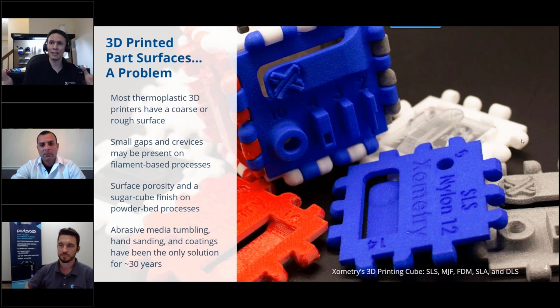Which, unlike cutting parts down from a solid blank of material with a smooth tool that leaves a smooth surface, I am taking a lesser material like a filament or a powder and fusing it up in order to create those parts. And inherently in that process, I'm building in small gaps and surface roughness from powder-to-powder interaction. There are ways to introduce things that can cause mechanical issues or even surface porosity that can cause issues with cleanliness, healthcare requirements, etc.